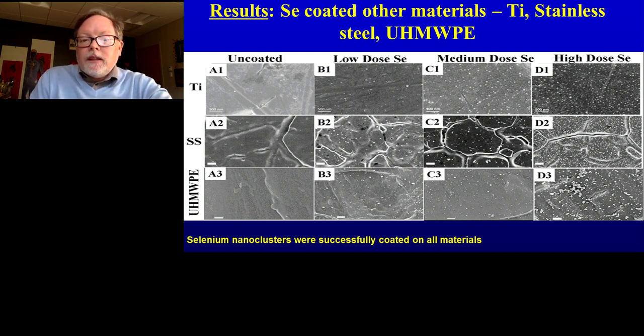You can see on this slide, going from the left to the right, uncoated versions of these metals and polymers, then a low dose of selenium. You start seeing a couple of white dots, then medium dose, high dose. You see more whites, and they're effective at reducing bacteria attachment. We've also seen them effective at reducing virus attachment. So things like Zika, Ebola, the flu virus, these selenium nanoparticles can keep those entities from absorbing, which again would reduce transmission from touch to touch on these surfaces.